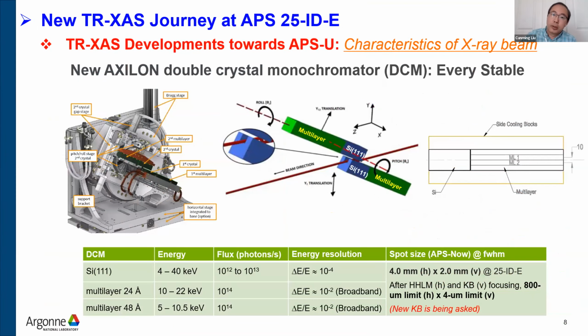Okay, now I'm going to show you the characteristics of the X-ray beam at this new beamline. Actually, this beamline has a really nice double crystal monochromator. It's brand new, very efficient and stable. This monochromator also has multilayer properties. This table shows you the energy range we can get from a silicon 111 double crystal monochromator and the multilayer beam, along with the flux and energy resolution.